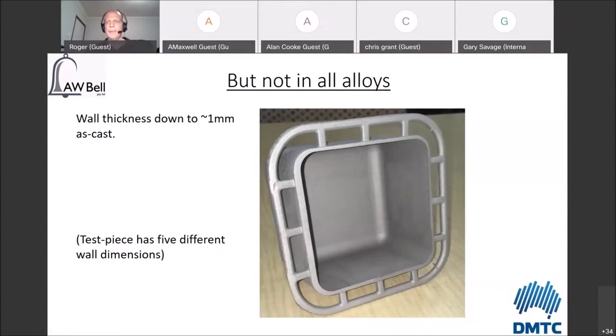You know, at the temperatures that we're using, we were actually filling these very, very fine fins. So it did tend to suggest that, well, maybe because we do know we have a problem with hot tearing, maybe we can do something about it and drop our temperatures a bit. So that became a focus of part of the next stage of the experiments.